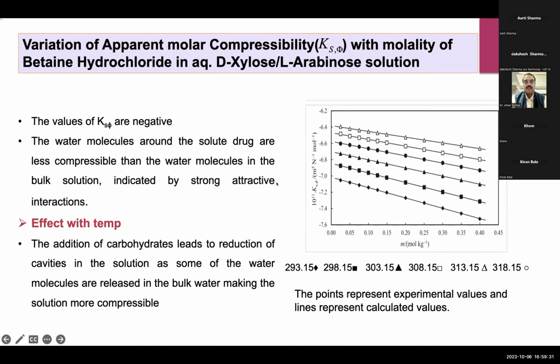The next variation was of the apparent molar compressibility with the molality of betaine hydrochloride. Ks,phi denotes the apparent molar compressibility, and the values were found to increase with molality. In this case, as the Ks,phi values are negative, with the rise in temperature the values become less in magnitude, but due to the negative sign, the values are increasing with respect to the concentration. Again, with temperature these values were found to rise, because addition of carbohydrates leads to a reduction of cavities in the solution, as some of the water molecules are released into the bulk water, making the solution more compressible. So the compressibility also increases as the temperature rises. As they become more compressible, that indicates there are some strong attractive interactions within the solution.